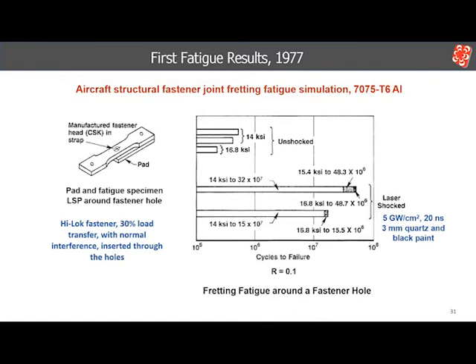When this specimen was loaded in a fatigue test, there was an elastic strain differential between the pad and the fatigue specimen due to the difference in their cross-sectional areas. This strain differential created a fretting action around the hole between the two clamp surfaces during each stress cycle. As can be seen, the results were very encouraging. After laser peening around the hole on both mating surfaces, the fatigue life was increased by at least 2 orders of magnitude at 14 ksi.